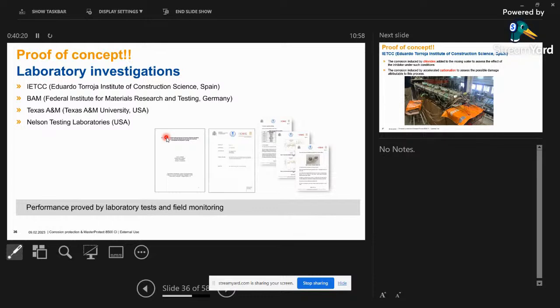So these are some of the extracts of the testing that has been performed, not only in the lab but also on field observations, both on the treated as well as on the untreated concrete samples. You will see that this technology is proven to be effective in corrosion mitigation or corrosion inhibition, not only in new structures, but also in old cracked structures or corroded structures. The result shows that it is more than 90% effective in reducing the corrosion current in cases of active corrosion. So that's the level of corrosion effect that it provides.